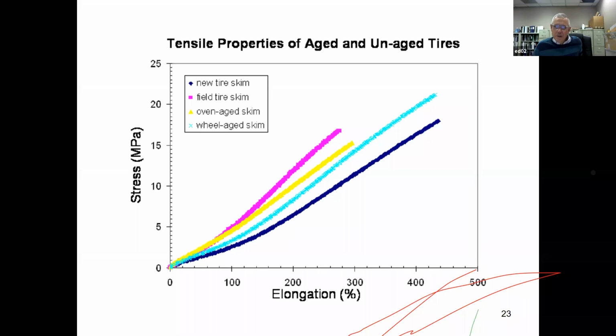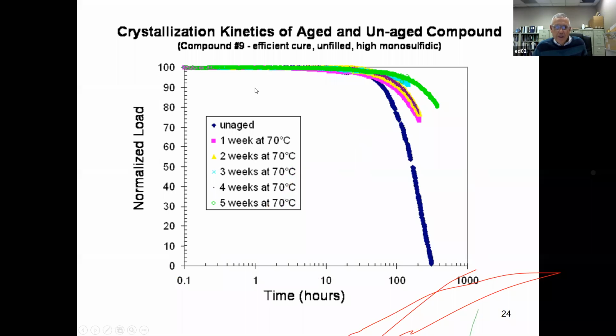So anyway, the next question we try to answer is why the decrease in the strength? And we said one idea we had was, you know, natural rubber, it's very important for natural rubber to crystallize on stretching. And so we measured the crystallization kinetics of aged and unaged. And so here, we stretch the sample, put it into the freezer, and then we measure the force as a function of time. This is a published technique by Professor Alan Gent.